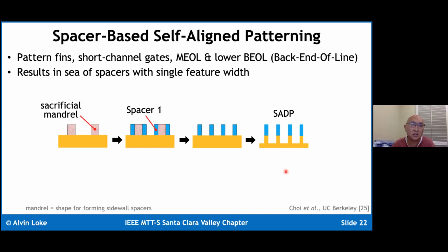So the way you do this is you start by patterning, using your 193 immersion lithography approach, a sacrificial mandrel, which you then do a spacer process on, and you grow these spacers on the sidewall of your mandrel. You then remove your mandrel, leaving twice as many spacers as you had mandrels, but at half the pitch. And then you proceed to use the spacer hard mask as a pattern for etching the underlying material.